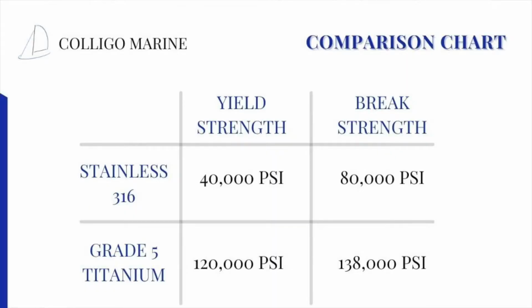boat. On the other hand, grade 5 titanium, which is what we use for chain plates, is not as forgiving, even though it's much stronger. The yield strength of grade 5 titanium is about 120-125,000 psi, but the ultimate tensile strength, or the break strength, is only about 135, 138. So there's only about a 10,000 psi difference from the yield strength to the ultimate tensile strength. So from the point it starts bending to the point it breaks, there's a much smaller window, unlike stainless steel.